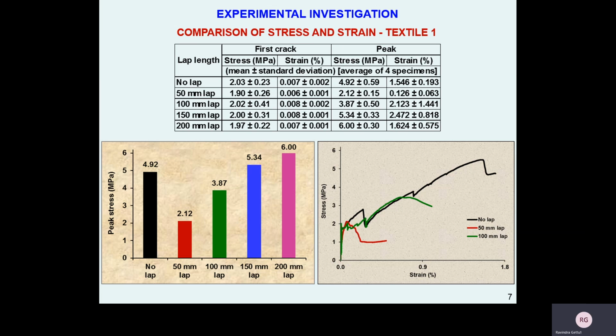Now with 50 and 100 mm of laps, the behavior is still inferior to the no lap case. The 150 lap is similar to no lap, and the 200 lap case is much better, which almost shows a response similar to that of a double layer.